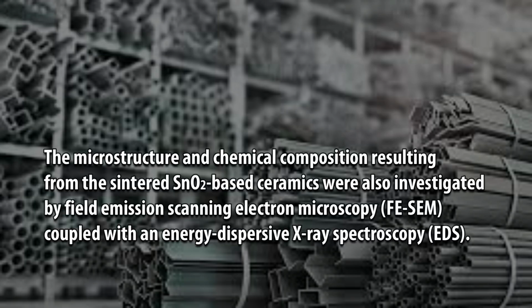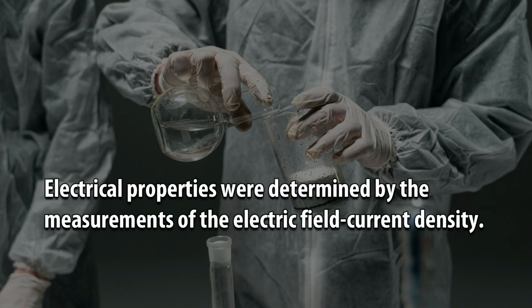The microstructure and chemical composition resulting from the sintered SnO2-based ceramics were also investigated by field emission scanning electron microscopy, FESEM, coupled with energy dispersive X-ray spectroscopy, EDS. Electrical properties were determined by the measurements of the electric field current density.